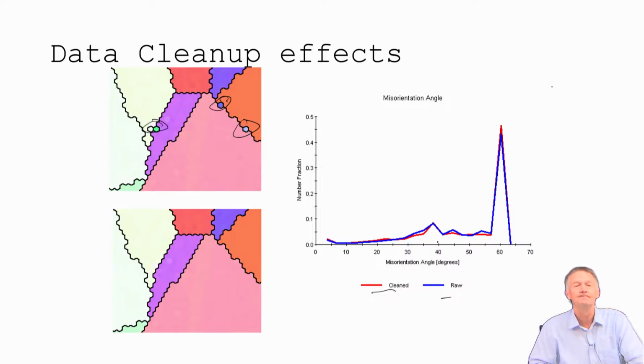Why not decrease the step size? By decreasing step size, you minimize the error. And then it's much better than averaging. Maybe. I mean, if you do very small steps, maybe you'll just get a lot more bad points along the boundary because you'll be taking a lot more points on the boundary.